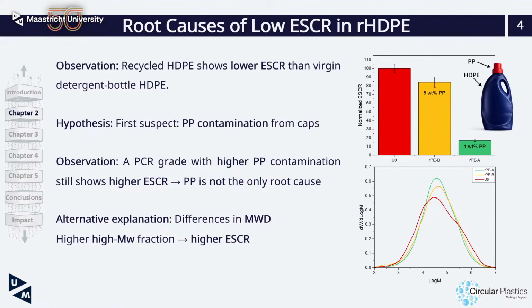Let's first start with the first question. Why do we have low ESCR in recyclates of HDPE? In the recycling world, the common explanation usually is contamination. And in this case, of course, we have PP contamination, polypropylene, coming from the bottle caps. And we usually end up with recyclates that have some levels of PP contamination. However, if you look here, you see that a polymer with a higher concentration of PP contamination shows higher ESCR. It seems contradictory, and it means that PP contamination alone cannot explain this difference. There should be something else as well.